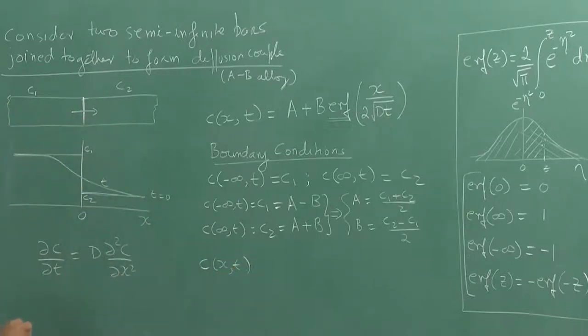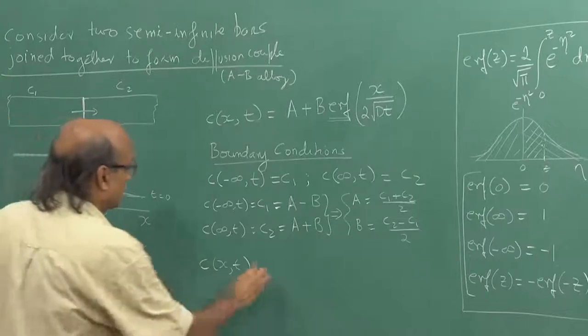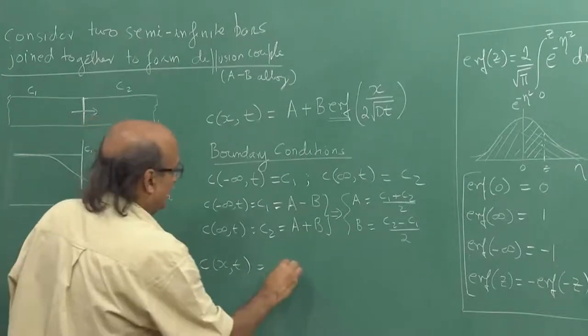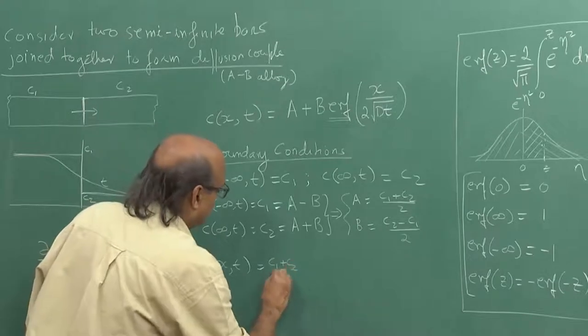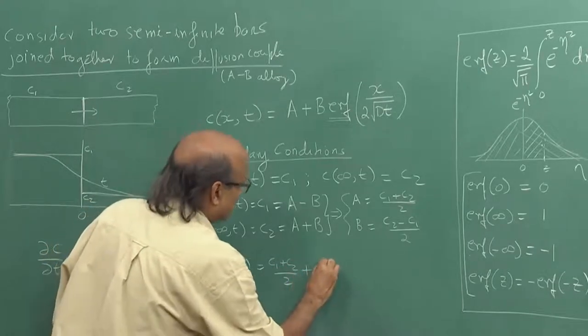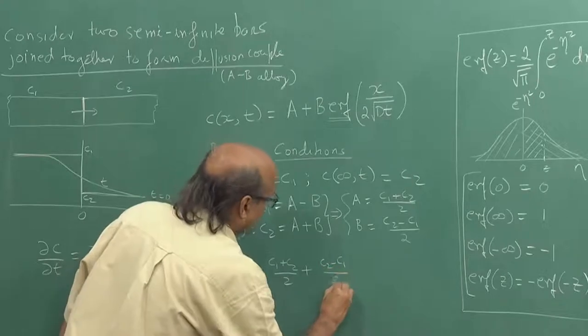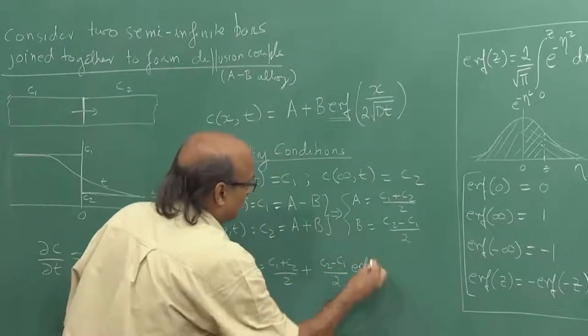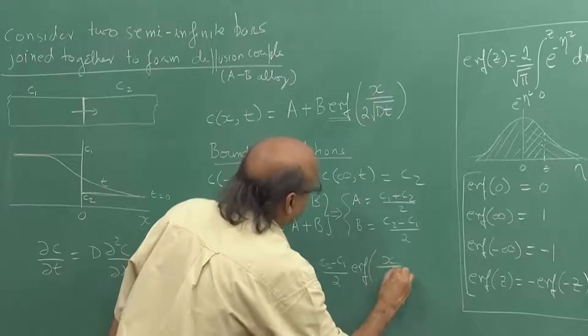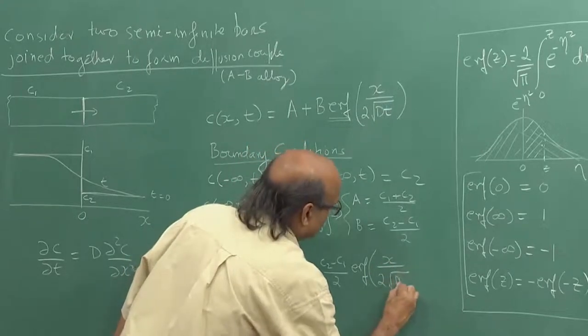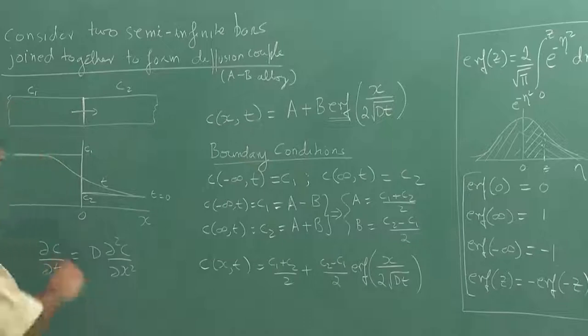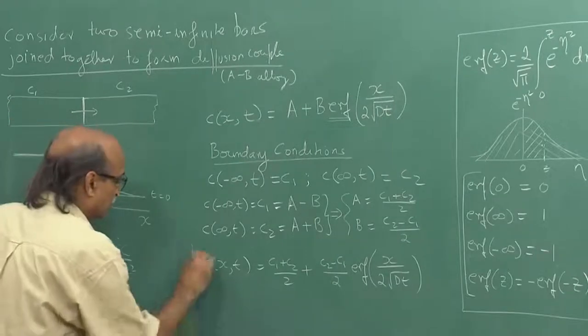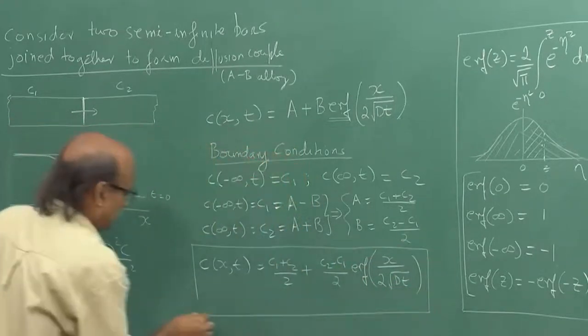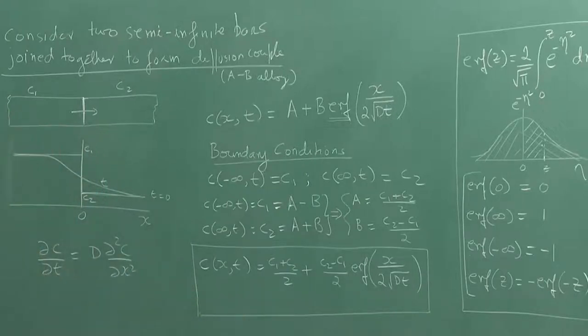Hence, now we have it that the concentration profile of the B atoms in this diffusion couple is given by C1 plus C2 divided by 2 plus C2 minus C1 divided by 2 error function of x upon 2 square root of Dt. So, this gives me the solution of how the concentration is going to change in a diffusion couple.